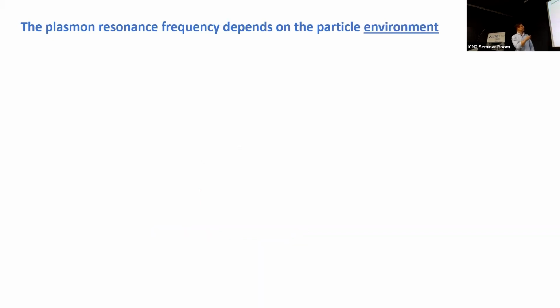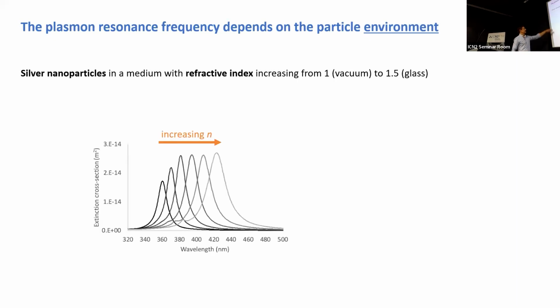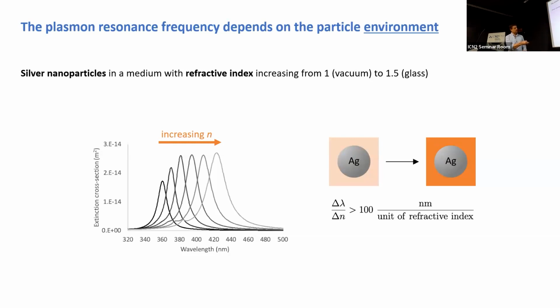Now, the final thing is that plasmon resonance can also be tuned by the environment. So you take a silver nanoparticle, I think this is also probably 10 nanometer, and you vary the refractive index from 1 to 1.5, let's say from vacuum to surrounded by glass. There's a huge shift in the plasmon resonance, which can be used to detect, for example, small changes in the refractive index where you have a delta lambda over delta n that is larger than 100 nanometers per unit of refractive index. So this can be used, for example, for glucose monitoring,